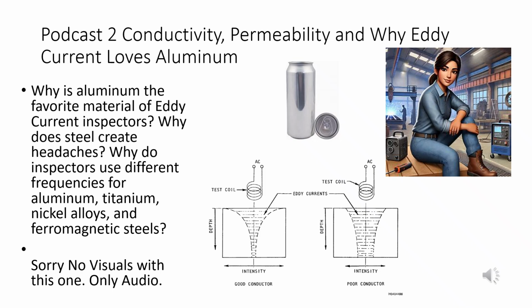Let's imagine the probe is producing a magnetic field. The field enters copper. Copper responds aggressively. Strong eddy currents are generated. Strong secondary fields develop. The primary field is opposed strongly. Penetration becomes shallow. Now let's switch to titanium. Titanium doesn't conduct well. The same magnetic field produces weaker eddy currents, weaker secondary fields, and deeper penetration. Same probe, same frequency, completely different behavior.